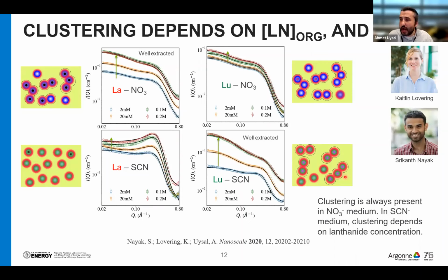And basically, we hypothesize that this might be the reason of the complete reversal in the system. There are different mechanisms. There is no change in the organic phase, so the selectivity in nitrate system should be determined by the aqueous phase chemistry. On the other hand, there's a more complex process determining the selectivity in the thiocyanate case. So we will be focusing on the thiocyanate a lot because it's a very interesting ion, and understanding its interfacial behavior will be very helpful.